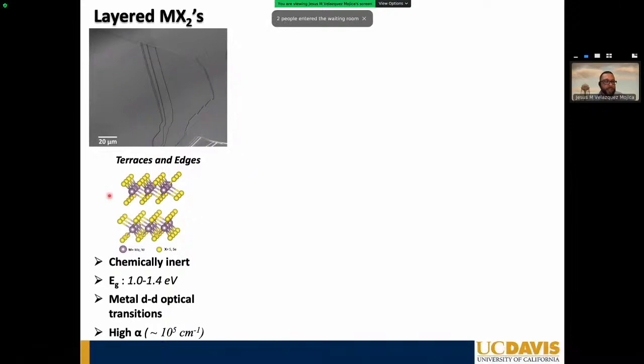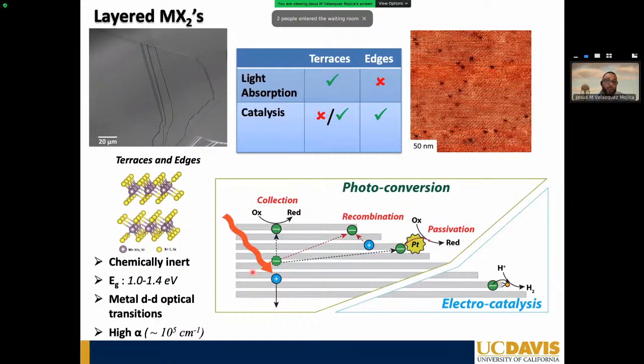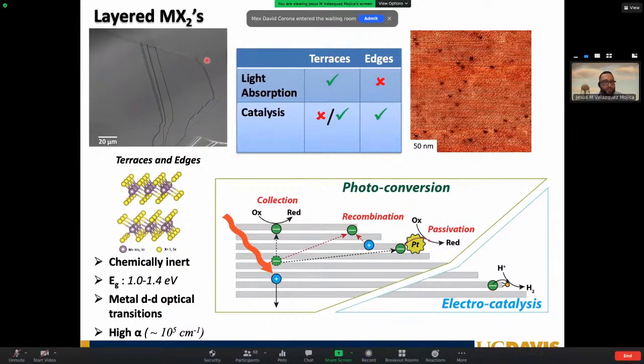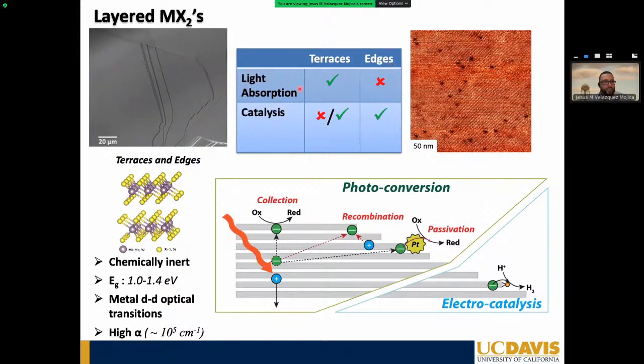We have taken advantage of this layered structure and also the fact that we get to fine-tune, depending on the crystal phase, whether we could synthesize a 2H semiconducting phase and have narrow band gaps that could be used as photocathodes, or we could actually synthesize a 1T molybdenum disulfide metallic phase, which gives us the opportunity to have a versatile metal surface for electrocatalysis. What I just described, actually this little table here, gives us a decent idea of how terraces, which are the flat areas, and edges, which are these under-coordinated sites, how they react, or I should say behave, under electrochemical and photoelectrochemical environments. This little table has taken about 50 years to put together.